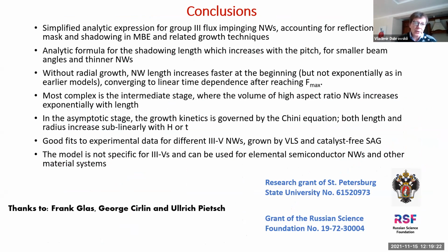So finally, my conclusions: a simplified analytic expression is given for group 3 flux impinging on nanowires, accounting for re-emission as well as the shadowing effect in MBE. An analytical formula is given for the shadowing length versus different parameters. Without radial growth, we can analytically calculate the growth kinetics, and we can see that nanowire lengths increase faster at the beginning, but not exponentially as in the earlier models, then converging to linear time dependence after reaching Fmax, the maximum flux. Most complex is the intermediate stage, where in some time the volume of high aspect ratio nanowires increases exponentially with the length, with the only fitting parameter being lambda, the diffusion length.